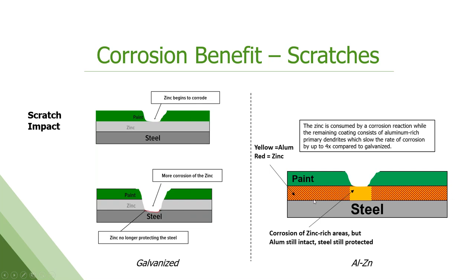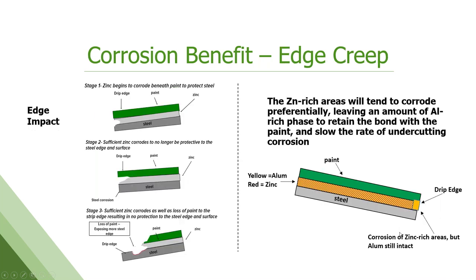However, with the aluminum zinc product, in this example, the yellow is the aluminum and the red would be the zinc. You get the same scratch and yeah, that zinc part goes away, but you're still left with all this aluminum that's protecting the steel and gives something for the paint to still attach to. So you don't see quite the degradation that you get on straight zinc. The rate of corrosion is slowed by four to nine times compared to galvanized, depending on the environment it goes into. Same thing on the drip edge or a cut edge, which is really the greatest risk out on a roof application.